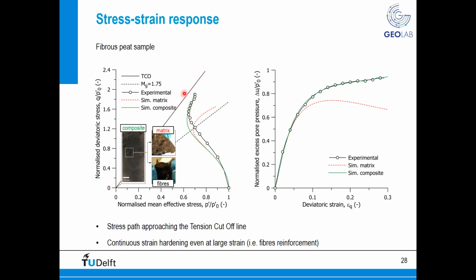The tension cutoff line, for those of you who are not familiar with it, is a line in which the horizontal effective stress is equal to 0. So if you transfer the tension cutoff line into friction angle, you end up with a material with 90 degrees of friction angle, which obviously doesn't make sense in terms of assessment. We cannot assume a material with 90 degrees of friction angle when we are performing our stability analysis.